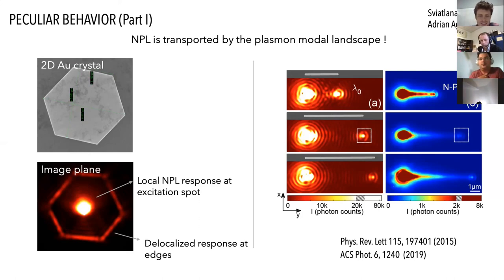It's a good suggestion. However, Jonathan, the plasmon is still key here. I'm not going to be showing the results here because I don't have them on this slide, but I encourage you to look at these papers. We really went into a deep understanding of what's going on. If we don't have a plasmon excited, say we change the polarization or we change the location of excitation in order not to favor the excitation of the plasmon, yeah, it is the heat source. The field doesn't have to go all the way to the other side of the structure because the heat will do it itself. That's my point.